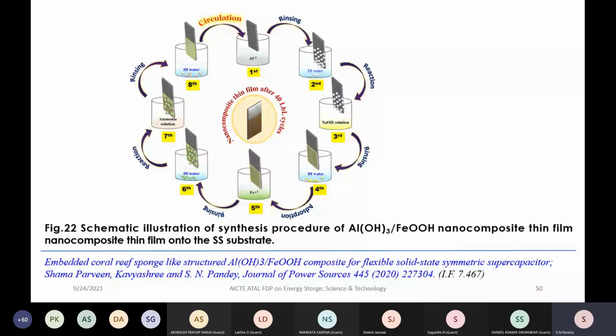This is the dipping in the solution having the aluminum ion, then rinsing it with DI water, then reacting with the NaOH. Then the aluminum hydroxide will be formed. Then rinsing with DI water. So the layer of aluminum hydroxide has been formed with the help of these four beakers. Then we dip it to have the adsorption of the iron, then again rinsing, then the reaction with the ammonia solution to have the FeOOH. In this way, one cycle is completed.